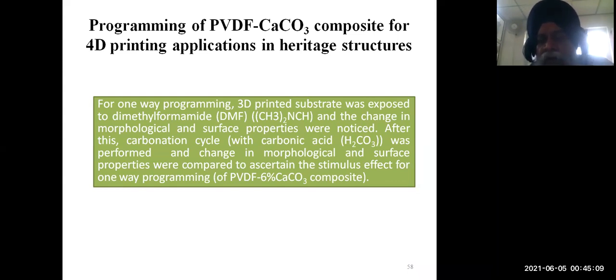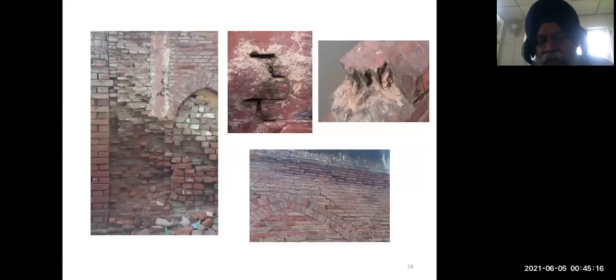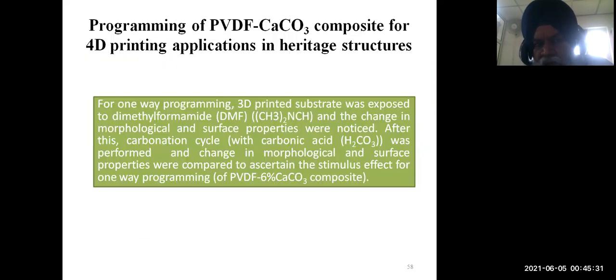What we observed is that in these types of structures we have a weathering effect, and one of the basic weathering effects is what we call carbonation. Basically, the carbonic acid, H2CO3, really contributes to the damage of these structures. So what we proposed as a 4D material is PVDF reinforced with CaCO3, at 6% CaCO3 by weight. We calculated this based upon the rheological property, after a series of experiments.